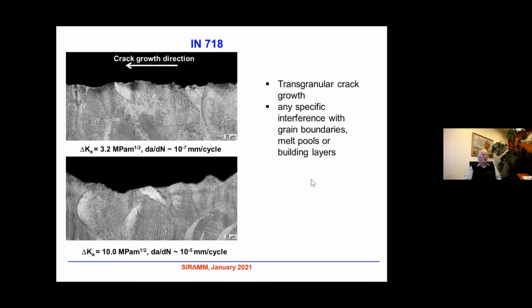But now I would like to show you the fatigue fracture surface. This is the crack growth direction here. You can see that the crack is running through this microstructure, and there is no specific interference with grain boundaries, melting pools, or so on. Simply, the crack is running through this microstructure and is practically governed by the finest features of this microstructure.